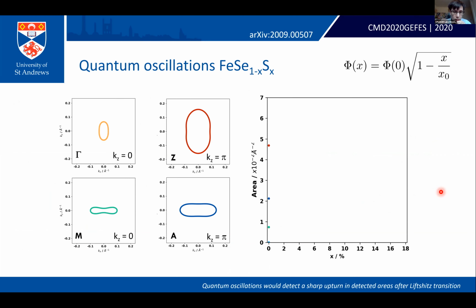So to show you this, what I'm going to do is simply plot the areas of the hole and electron pocket at both the kz equals 0 and kz equals pi states of a model of iron selenide which has been fit to the experimental ARPES data. And then we're going to apply a mean field nematic order parameter term, where 18% is the pure tetragonal state and 0% is the pure nematic state, and see how these areas evolve.